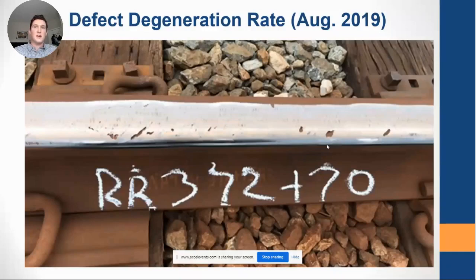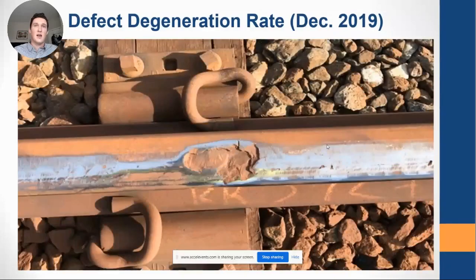And lastly, on the next slide, as mentioned, only a short 4 months after the flaking and spalling, in December of 2019, you can see this sizable chunk of the rail that came out. So 4 months from our negative hand test, there was a rail surface breakout. Thankfully, this was removed prior to any further deterioration or, in the worst possible condition, a broken rail.